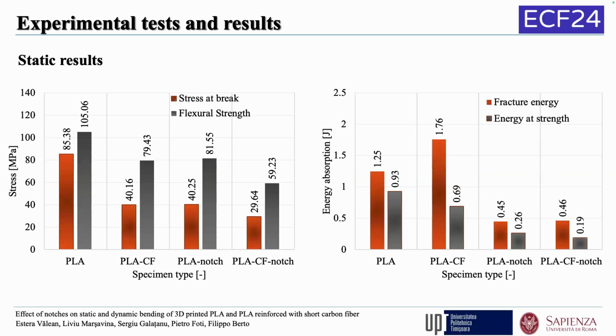We determined the stress at break, the flexural strength, for all the materials. So the highest value, as you can see, more than 105 megapascal, is for the PLA, and then we have the value for the PLA reinforced with carbon fiber, which is around 80. The energy absorption is the only property that is higher for the reinforced specimens, for both notched and unnotched specimens.